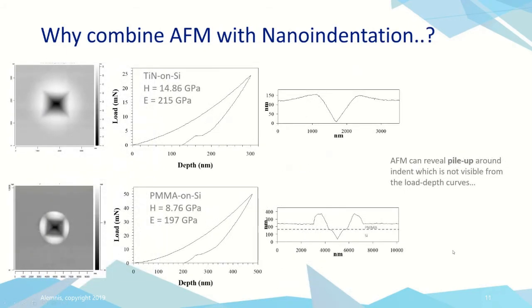Here's a couple more examples just to highlight the importance of being able to understand if there's pileup or sink-in around the indentation. Now, both these curves are made on two materials. One is a hard coating, titanium nitride on silicon, and the other is a soft polymer, polymethyl methacrylate, also on silicon. Now, we've gone through the indent into the substrate. That's why we see this step on the unloading curve. This is a phase transformation, pressure-induced phase transformation in the silicon.